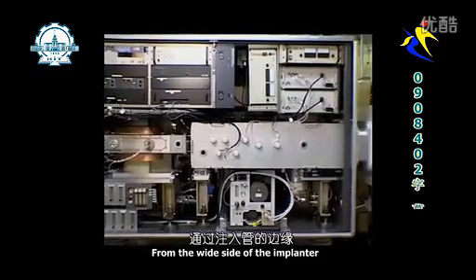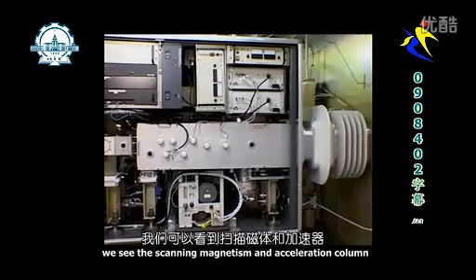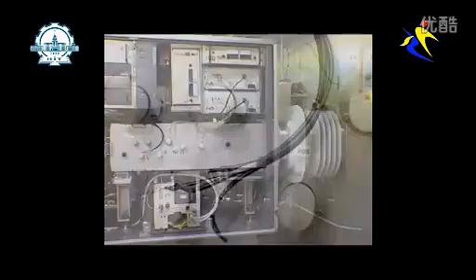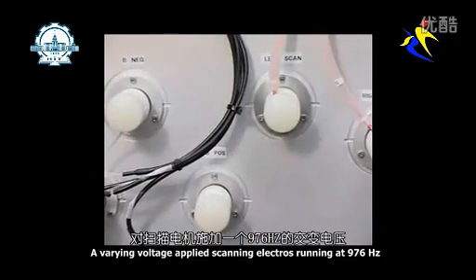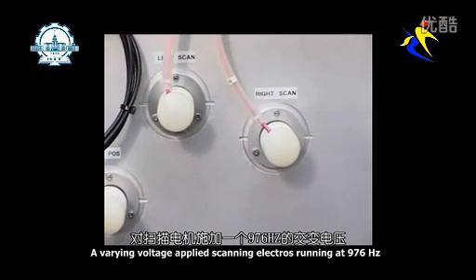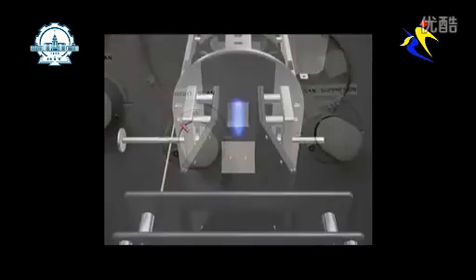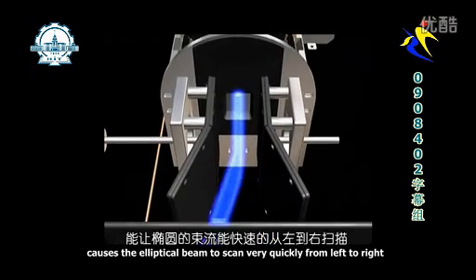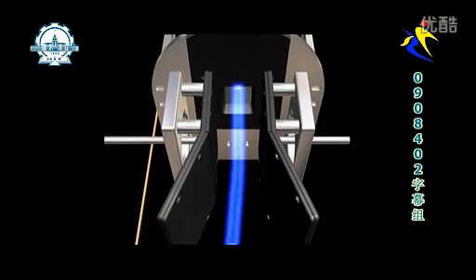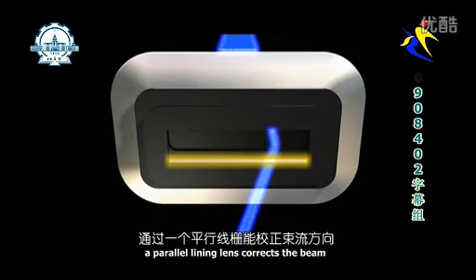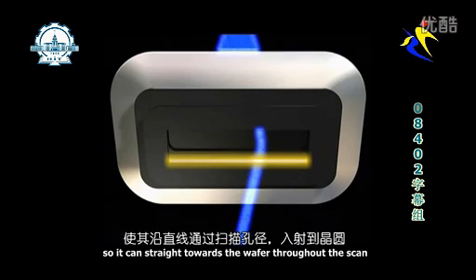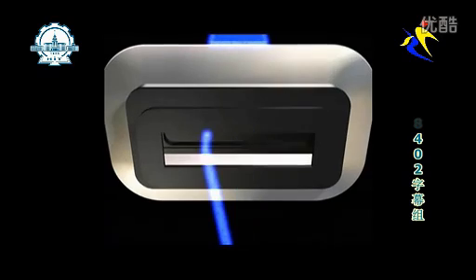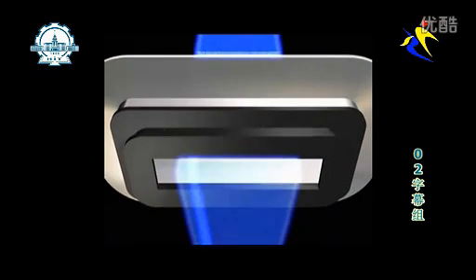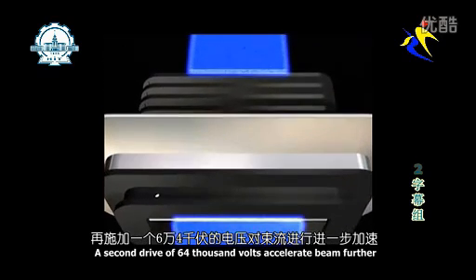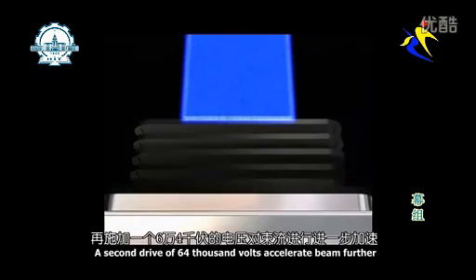From the right side of the implanter, we see the scanning mechanism and acceleration column. A varying voltage applied to scanning electrodes running at 976 Hz causes the elliptical beam to scan very quickly from left to right. A parallelizing lens corrects the beam so it heads straight towards the wafer throughout the scan. A second drop of 64,000 volts accelerates the beam further.